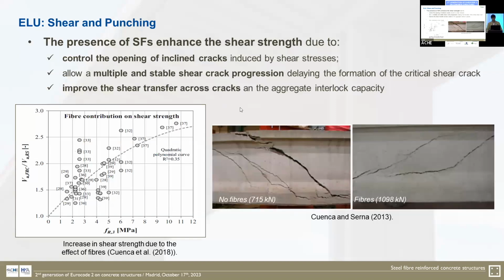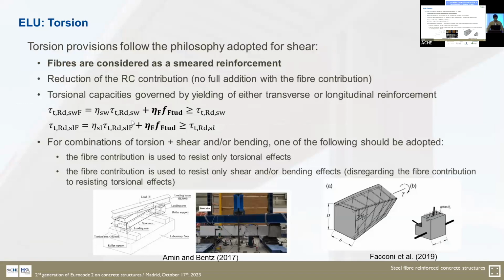As for shear and punching, the use of steel fibers improves the control of the crack width of the shear crack, and also the aggregate interlock. This has been seen in tests, and the higher the FR3 value, the higher the contribution of the fiber reinforced concrete to the shear strength. The model accepted in Annex L for taking into account the contribution of the steel fiber reinforced concrete is also based on the critical shear crack theory, and this is the formulation.